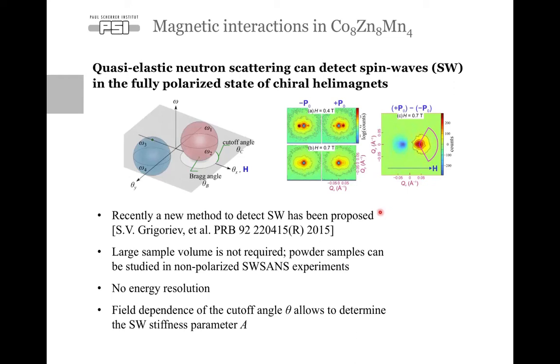And it doesn't require large sample volumes, though of course you can only measure materials with relatively low exchange stiffness. And the only parameter you can measure in this way, by measuring the field dependence of this spin wave scattering pattern, is the exchange stiffness. You cannot deduce higher order exchange interactions.